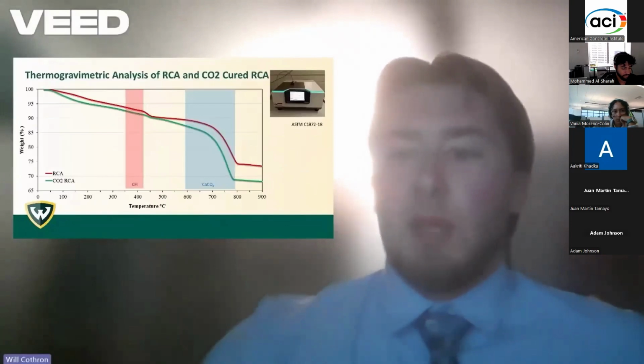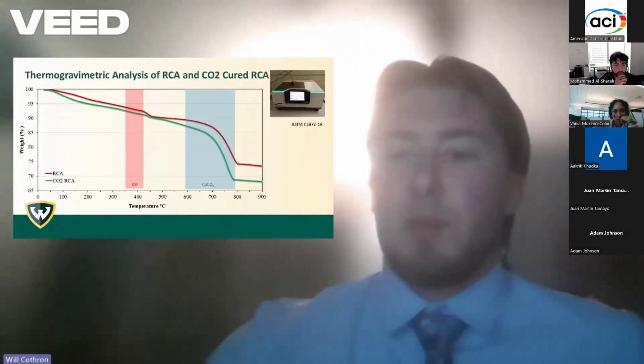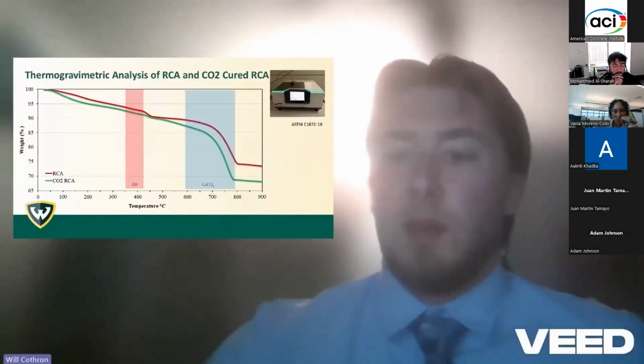To verify the carbonation treatment of RCA, we performed thermogravimetric analysis on the RCA and carbonated RCA mortar surface. TGA is a technique that measures how a material's weight changes as it is heated. This helps us identify different chemical compounds present in the materials. In the graph, the red line represents untreated RCA and the green line represents RCA treated with CO2.